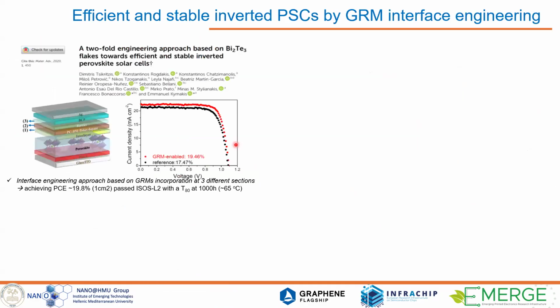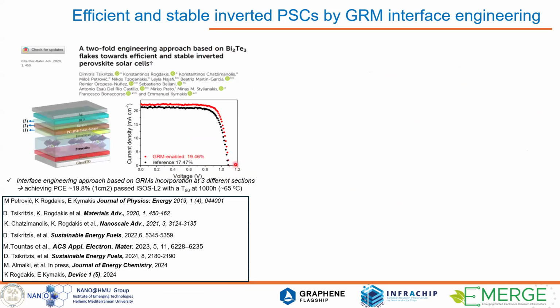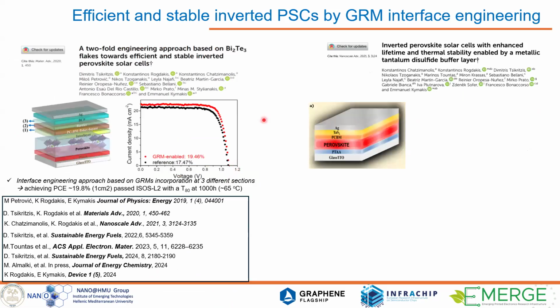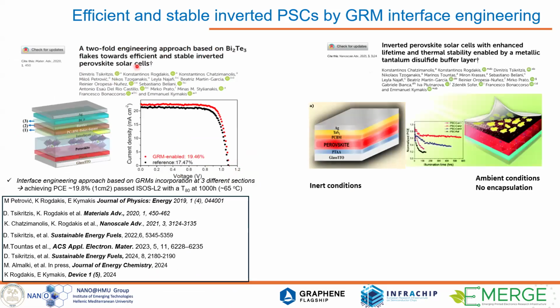Very briefly, we have a series of applications with our colleagues from the last 5-6 years. One example was bismuth telluride flakes or nanosheets that were integrated as a dopant of PCBM, the electron transport layer, and also as a barrier between the silver pad and the active layer. Both of these approaches allow us to increase the efficiency and the stability of the devices.